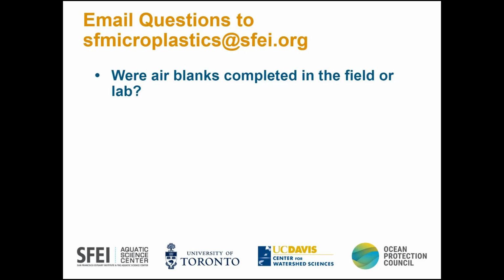Chelsea, do you want to add to that? I think the only thing I would add is this question specifically asks about air blanks. So instead of putting petri dishes out to collect dust in the air from our lab, the way we did our blanks was we ran a sample that was similar to our samples through the whole process. So, for example, we would put RO water through the entire process of extraction, counting, sorting, all of that. And we've done air blanks basically to test how well our HEPA filter was performing. But I think the best method for really being able to compare apples to apples with your samples are representative sample blanks and field blanks.